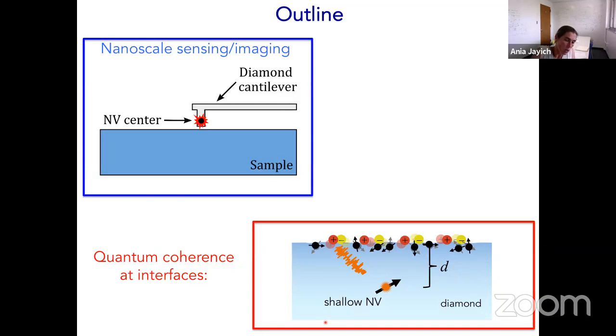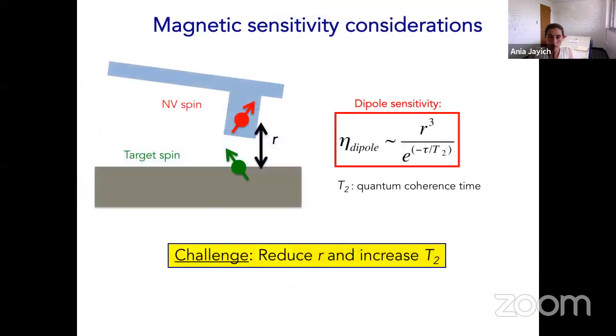Okay, so in the last few minutes, I will quickly go through quantum coherence at interfaces. I'll go through this a bit quickly because I think a lot of these are probably fairly well understood. If we want to have really high spatial resolution and really high sensitivity, we want to bring our NV center as close as possible to our target system. That means that we want this distance r to be small, because our dipole sensitivity gets much smaller. Sensitivity to small numbers of Bohr magnetons will go as r cubed over e to the minus tau over T2. So the challenge is we want to make r small and we want to make the T2 long.